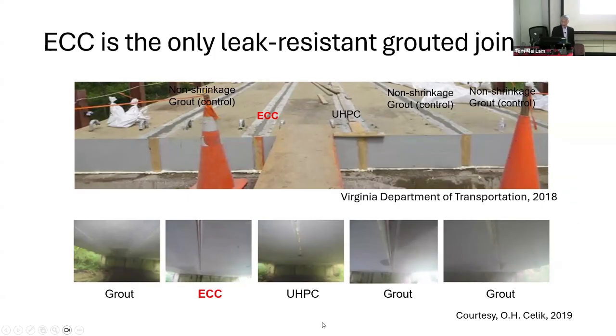Dr. Selig told me that they have problems with leakage of their typical grout, which is used to grout the connection between these steel box beams fit together by shear keys and used as a bridge slab overall. They get water leaking through these joints, which causes durability problems. So they were looking for a solution, and in this study they used their conventional grout, UHPC and ECC. What they reported was that ECC was the only grouting material that did not have any sign of leakage. All the others have leakage problems.